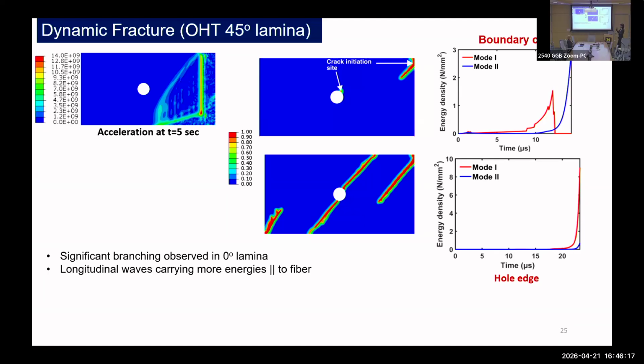If you compare the 0 versus 45 degree, you will see the 0 degree has way more branching, as you have observed. That is quite expected because in that case, the impacting wave was propagating parallel to the fiber direction. So it was much faster and carrying a lot more energy. So it has a lot more energy to create more branching.